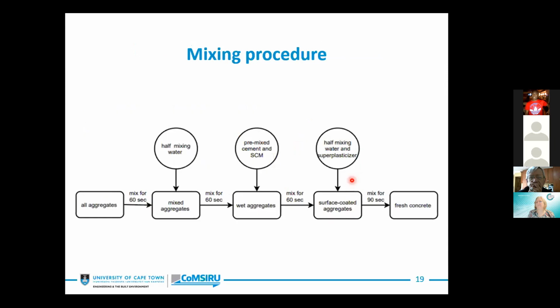Here's a graphical representation of what our sieves, our binder sizes look like. So for mixing, the mixing procedure adopted for this study is a modified version of the two-stage mixing approach developed by Tam et al. The procedure basically involves pre-mixing aggregates in water and pozzolanic slurry to provide more interaction between the recycled aggregates and the binder. Studies have shown that this procedure enhances pore filling and increases pozzolanic reaction. Also, premixing allows fine recycled aggregates to take up moisture without getting to saturation within a few minutes. Literature has shown that some 60 to 70% degree of saturation is required for optimum recycled aggregates concrete performance.